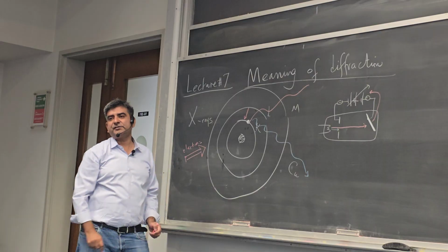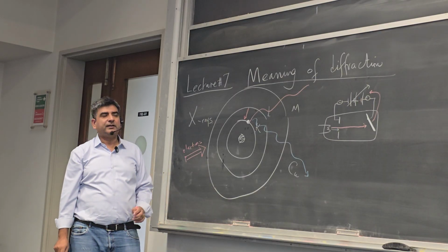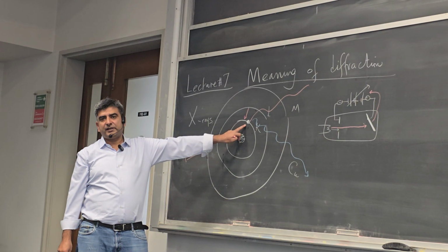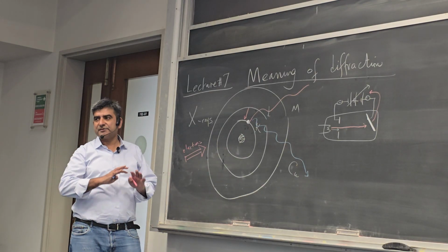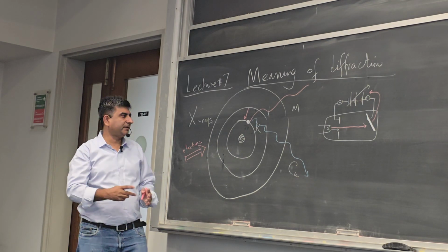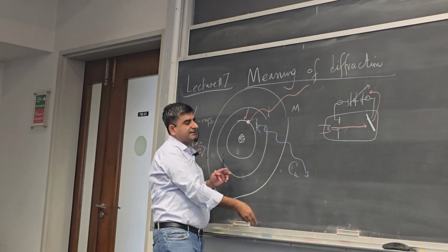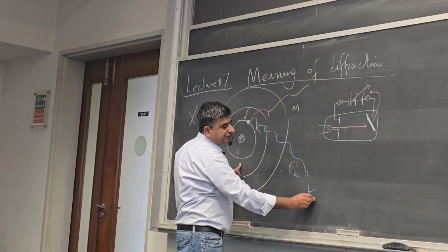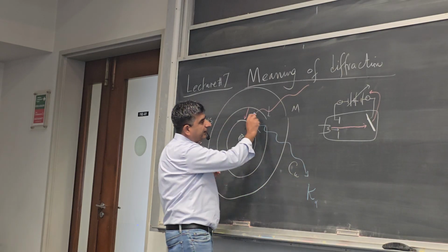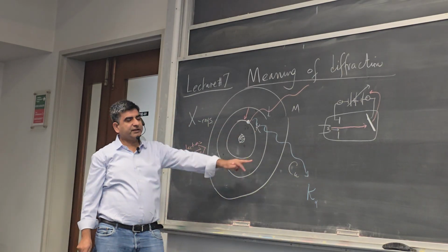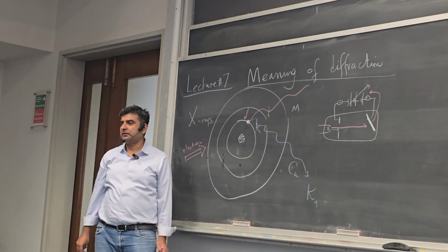Okay, this radiation is X-ray. Since it falls down into the K shell, this radiation has a certain wavelength which depends upon the atomic number of this material and this shell. Since it fills the K shell and comes from a neighboring shell, the L shell, this radiation is called K alpha X-rays.